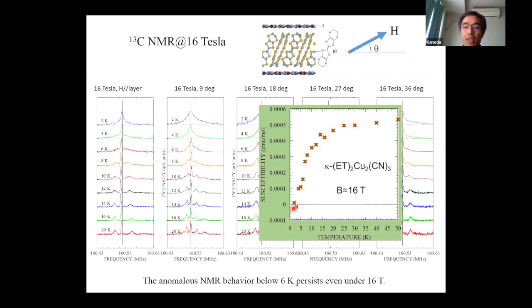This may suggest that the quantum spin liquid has an instability to singlet ground state, singlet formation. An important point is that this anomaly is very robust against magnetic field up to 16 Tesla. The phenomenon occurs at 6 Kelvin, but 16 Tesla does not affect the transition temperature.